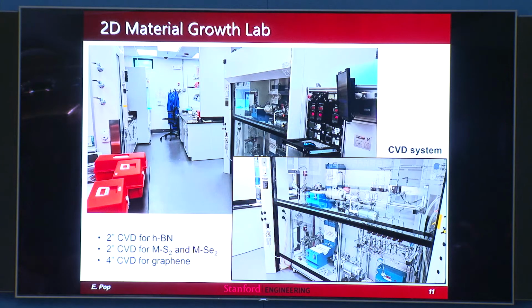This is what our growth lab looks like. This was actually something we set up when I moved to Stanford 5 years ago. It's all fully operational right now. This is the selenides growth, and this is the boron nitride growth down there. I'm not showing it, but we also have a 4-inch growth system for graphene, and we have a separate 2-inch system for growing the sulfides, the molybdenum disulfide, basically.